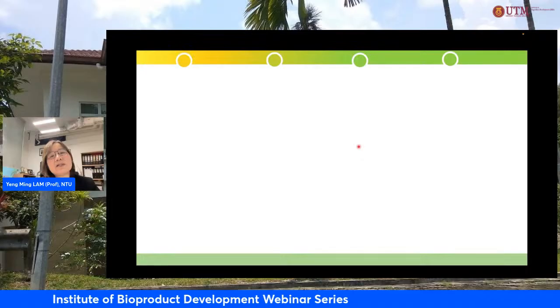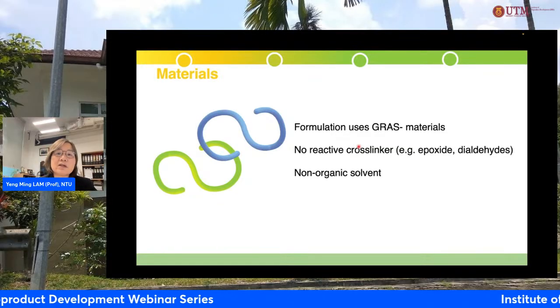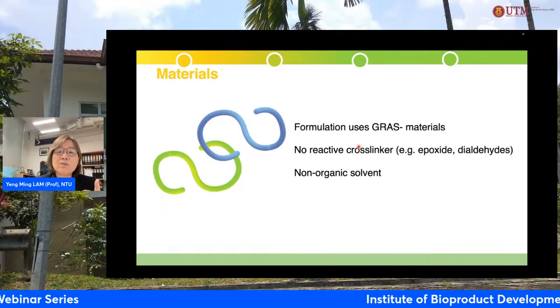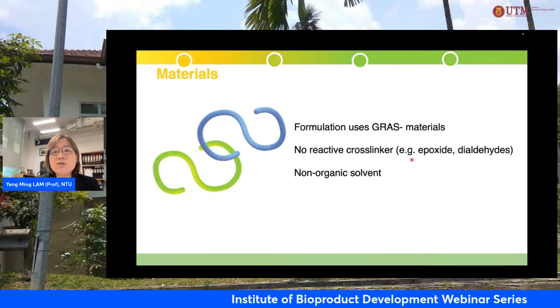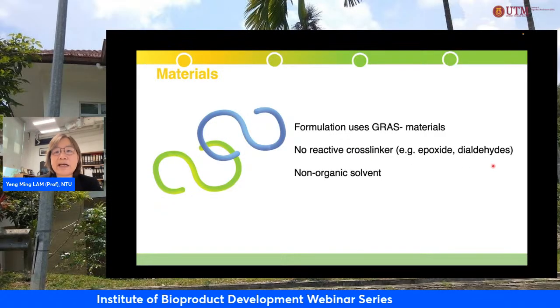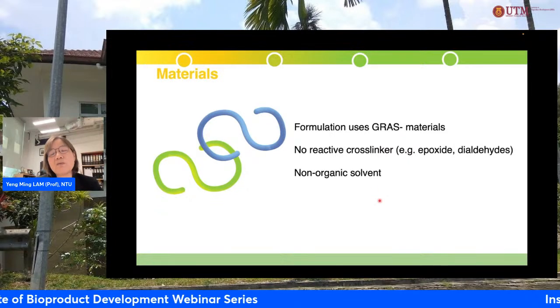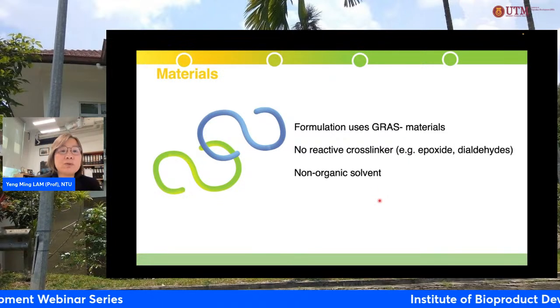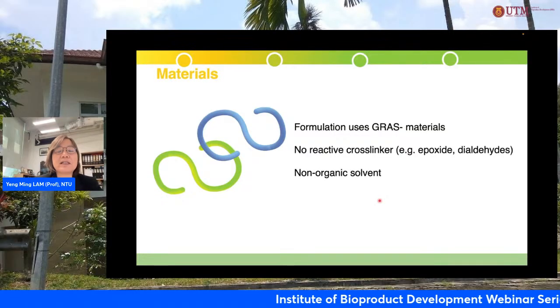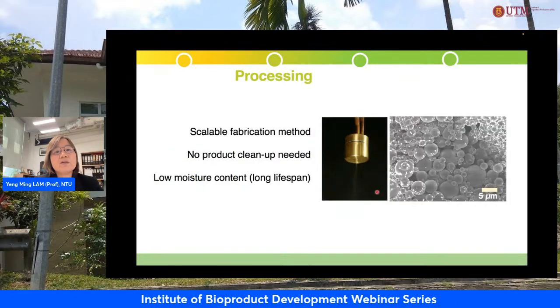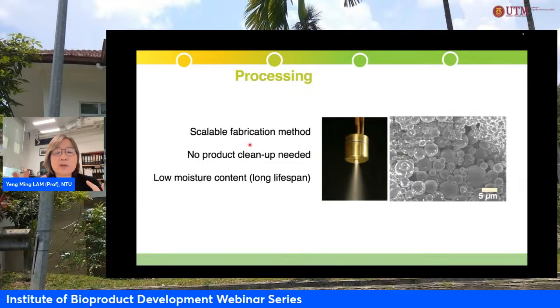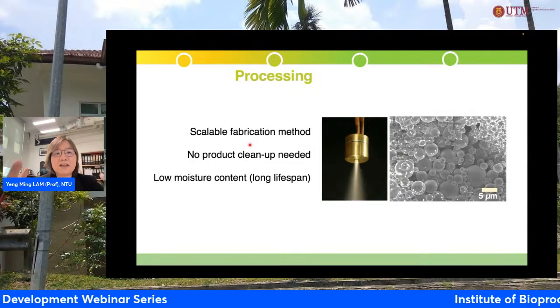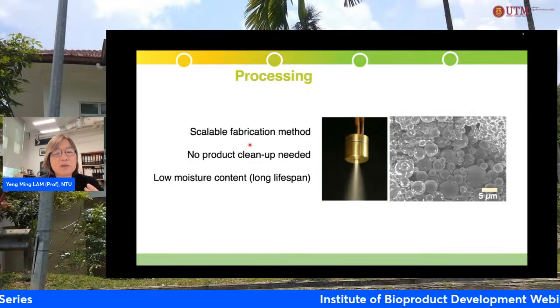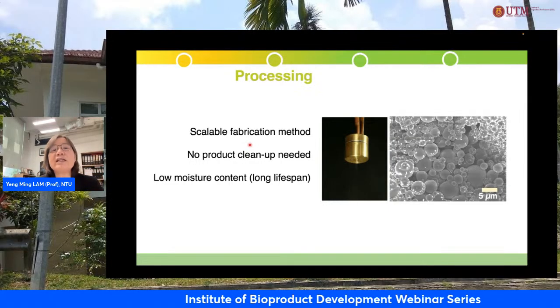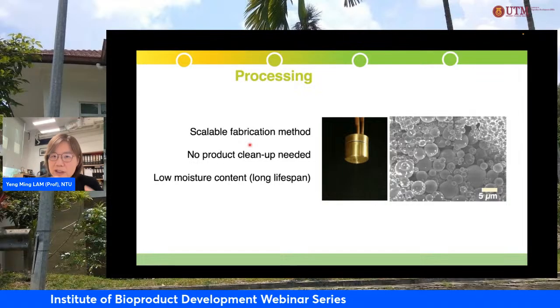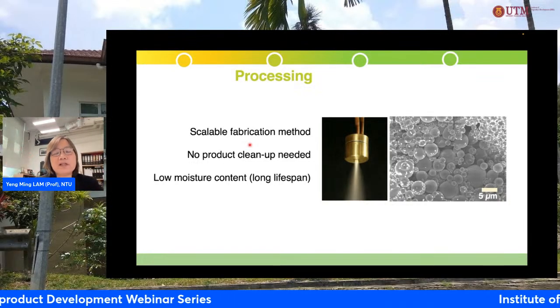So our solution essentially is to use a material which is considered GRAS material, which is generally regarded as safe. There is no reactive cross-linker, no epoxide, no dialdehydes, no organic solvent. The material that we use, we made using a platform where we do not use any organic solvent. There is no reactive cross-linker. It is a very clean platform. The simple production process is a fabrication process where we use spray drying to produce the powder. In fact, we are now producing it together with IBD, which is a very nice platform. And then there is no cleanup requirement. There's very little moisture content. Once you spray, you collect the powder. The powder is what you use.